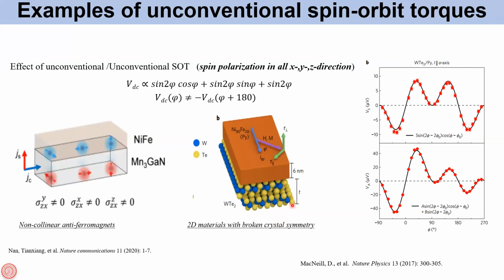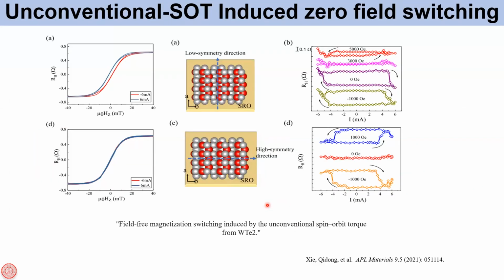Why we are interested in this unconventional torque is because it can lead to out of plane spin polarized current. This can then be used to switch perpendicular magnetic systems, which are mainly used in magnetic recording. Here is an example I have shown. There are many examples, but this is one where they used tungsten ditelluride, and they were able to switch at zero field. If you have a conventional torque, in order to break the symmetry, you need to apply an in-plane field. But if you have unconventional torque, you can achieve zero field switching, as they have observed in this example here. And here it was done with the low crystalline symmetry of WTe2.